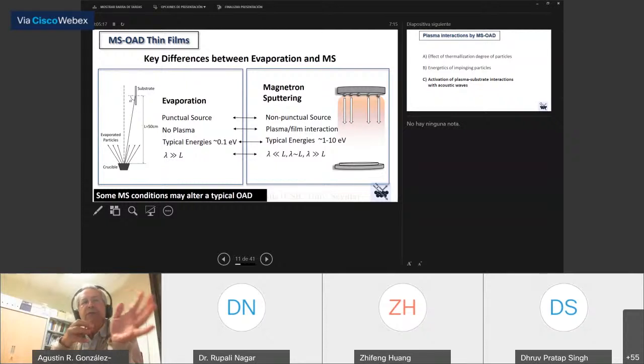It is clear that if we consider the characteristics of electron beam deposition and compare them with a magnetron sputtering configuration, there are substantial differences. For example, in evaporation we usually utilize a punctual source, while in magnetron sputtering the source is not punctual. Here we don't have any plasma and there is no gas. Here we have a gas and a plasma between the target and the substrate. In electron beam evaporation, the energy of the evaporated particles is on the order of 0.1 electron volts, while typical energies in a magnetron sputtering experiment range between 1 and 10 electron volts. And most importantly, while here the mean free path of the particles is practically unrestricted because we don't have any gas in the chamber, in this other situation the mean free path is much shorter.